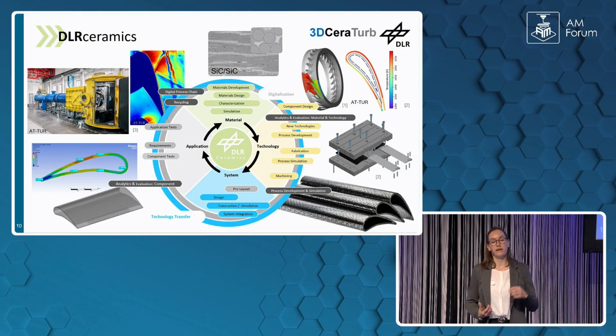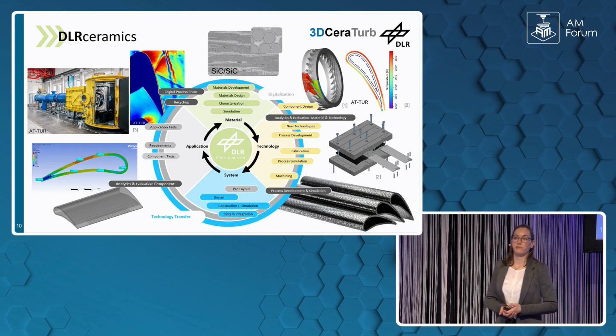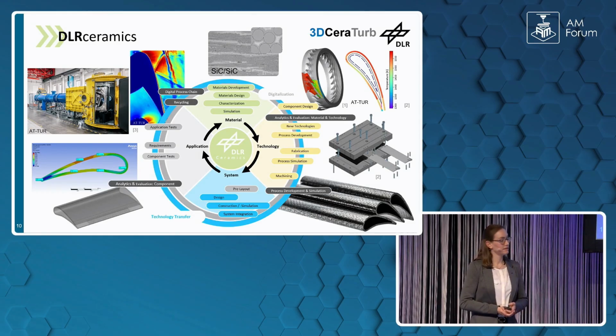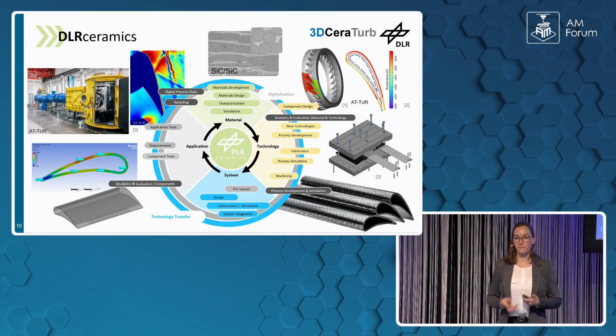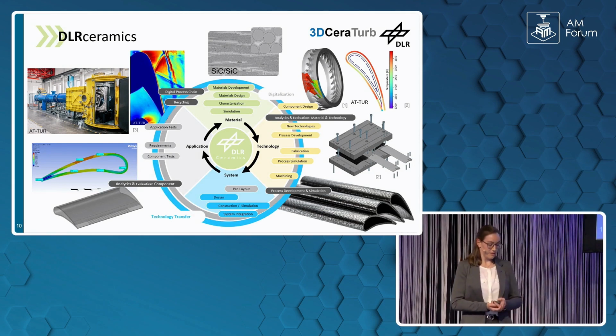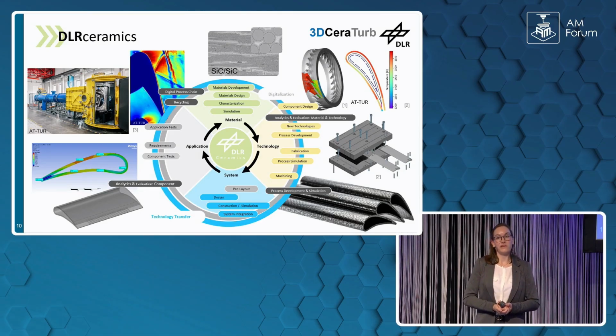Special toolings were fabricated, and after the successful manufacturing of turbine vanes, we added a grinding step of the outer surface to meet the high requirements for surface roughness, which comes from aerodynamics. Then laser-drilled cooling holes are integrated in the trailing edge, and the whole process is accompanied by stress analysis at different operating points. So we coupled CFD and FEA calculations for the stress calculations. Then, finally, DLR has the possibility to actually test the components in several wind tunnels to evaluate their performance and their cooling efficiency.